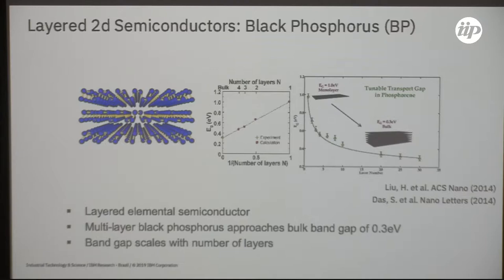We were particularly interested in extending the spectral range beyond what silicon photo detectors can offer. Silicon has a limit when it comes to detecting outside the visible spectral range — at some point the band gap of silicon precludes seeing in the telecommunications window. That's why black phosphorus could be interesting to build an imager or photo detector that allows you to see images where a silicon photo diode could not, making it a nice application for hyperspectral imaging.